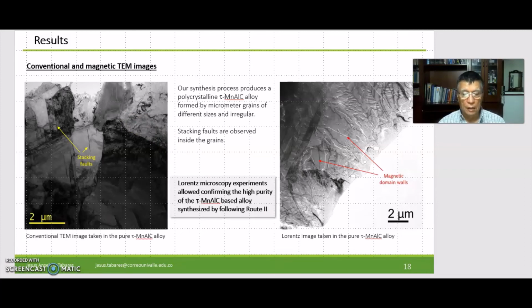In this figure, it is shown a Lorentz image taken in a region of the sample by making Lorentz microscopy, a TEM-based technique able to image magnetic contrasts of ferromagnetic materials. In this image, the bright and dark contrasts are produced by magnetic domain walls formed inside of the grains. As we see in this image, domain walls are formed inside all the grains, so that we could conclude all grains have the tau phase of the alloy.